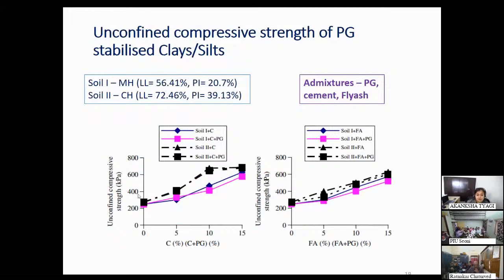But if we look at the strength aspect, unconfined compressive strength, for both types of soils the strength increased. And even if you use cement plus phosphogypsum, the results are quite close. So the encouraging thing about this preliminary study is, see, if this is 15%, so 7.5% is cement, 7.5% is phosphogypsum, and still it is comparable with the result when you're using 15% of cement. So the results are quite close. And for the fly ash and phosphogypsum also, similar results were obtained by the group of researchers. And this is a quite encouraging result.